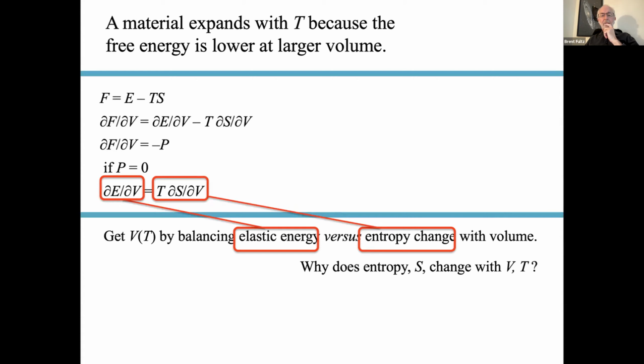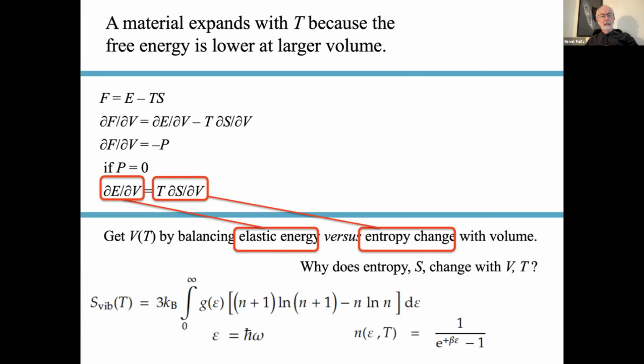So this is the big question now: why does the entropy at the stat mech level change with the volume? Well, the expression for a harmonic oscillator and its entropy and a distribution of them is here. We're in 3 dimensions times Boltzmann's constant. We need the phonon density of states, which is this G, it's normalized to 1. And this is the entropy effectively of mixing of bosons. There's a more familiar entropy of chemical mixing, but this is basically the boson equivalent for it, using the Planck distribution for the occupancy factor here instead of a concentration, let's say.